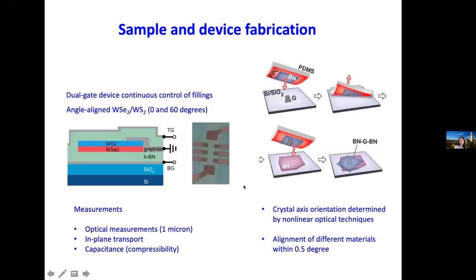To make sample devices, we use pretty much the same technique as twisted bilayer graphene. So we exfoliate monolayers on silicon substrates, and then pick them up and stack them. And we can use nonlinear optics to determine the crystal axis of those monolayers and then stack them with a very well-defined twist angle. And here is an example of a device. The Moire superlattice is embedded in hexagonal boron nitride, and then we can add top and back gates. And you can also put contacts on the Moire system.